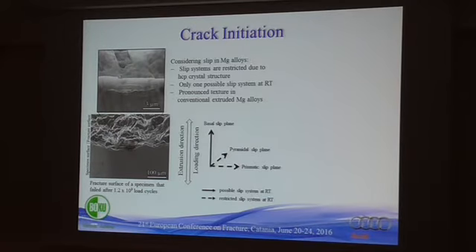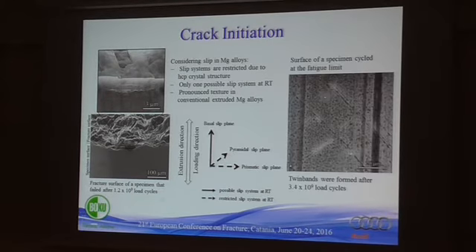But slip is not the only mechanism of cyclic deformation. There's also twinning, and indeed it has also been often shown that twinning plays an important role in magnesium alloys. We were also curious, and indeed we could observe these twin bands on the surface of a specimen cycled at the fatigue limit. And now this twinning, due to the reorientation of the crystal structure, can have a twofold effect. On the one hand, it can open new slip systems. On the other hand, it also can act as a barrier, causing dislocation pileup and subsequent local stress concentrations.